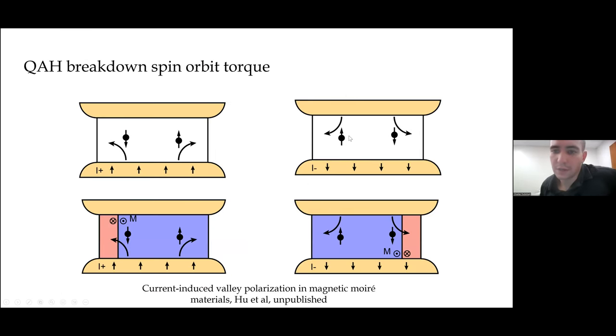We think what's going on in this quantum anomalous Hall system is something like that. The idea is that electrons that are injected into the quantum anomalous Hall system enter a chiral edge state. Under most circumstances, they stay in the chiral edge state. However, if electrons are allowed to enter the bulk, either because of this high bias effect or at finite temperature, or a temperature close to the activation gap, then you'll have electrons in the bulk that are experiencing this enormous anomalous velocity associated with the Berry curvature that's giving you your quantum anomalous Hall effect.